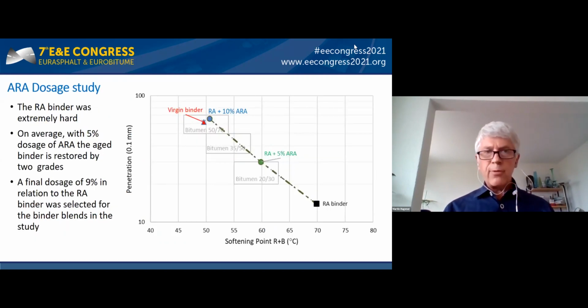So the first step was then a pre-study to determine the optimum dosage. So if we start with the reclaimed asphalt binder, we did add 5 and 10% of ARA, and you can see that with 10% we are a little bit above the virgin binder properties, a little bit softer. So we decided to use 9% for this interlaboratory study.